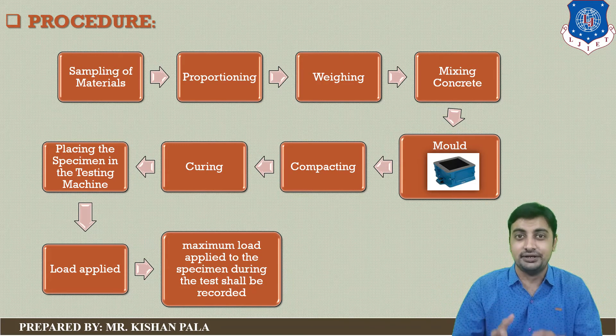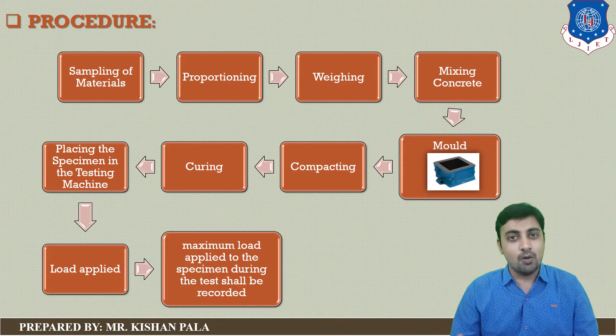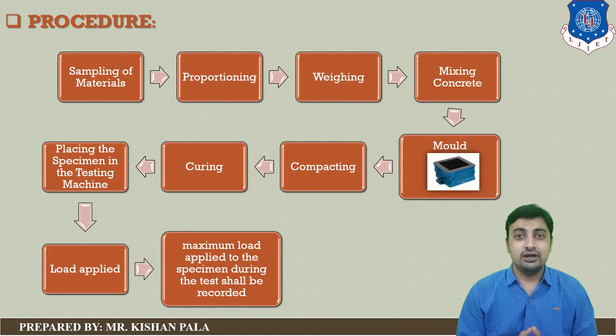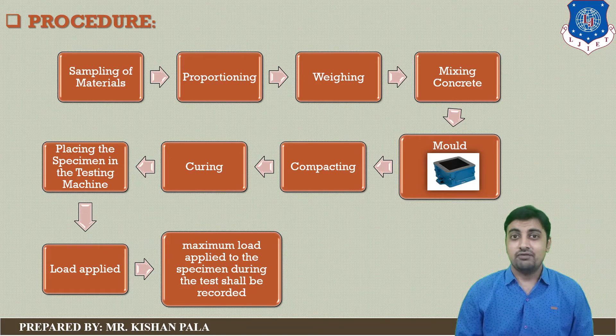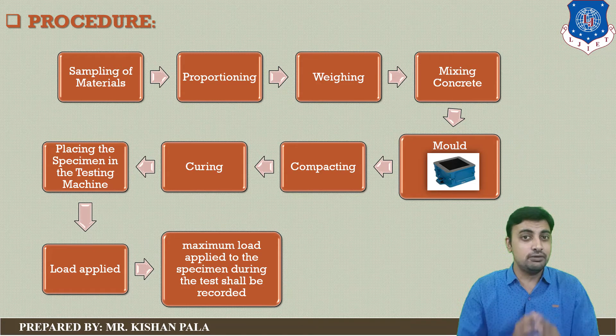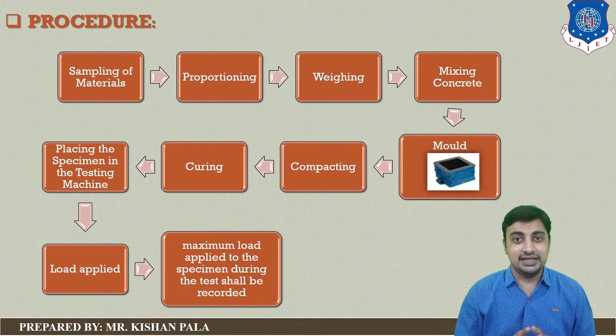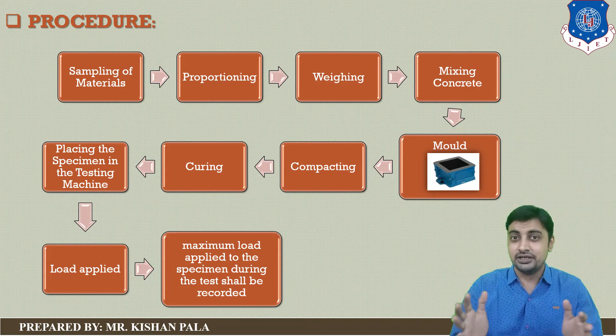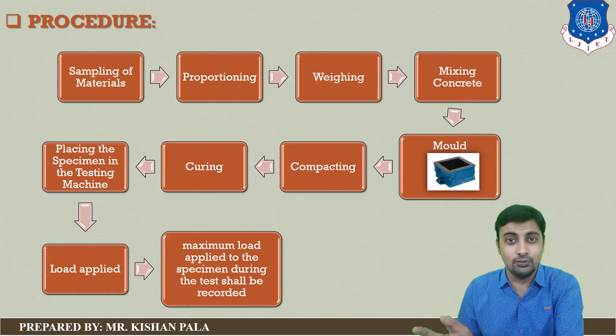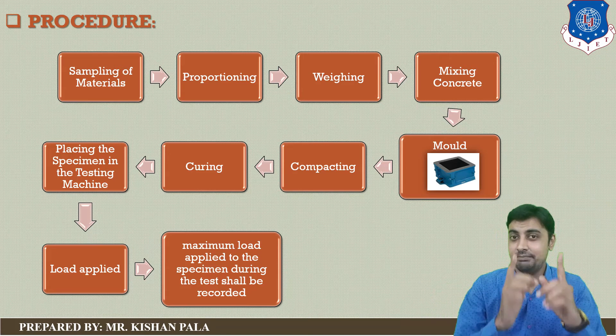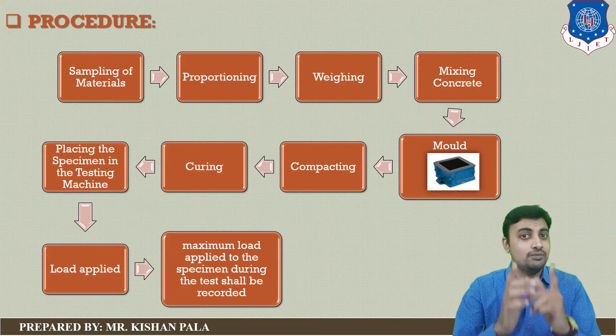After setting, you have to remove the mold from the concrete mass and place the concrete cubes in a curing tank to allow curing of the concrete mass. Generally, we find compressive strength at 7 days and 28 days, requiring 3 specimens for the 7 days and 3 specimens for the 28 days — that is, 6 cubes placed in the curing tank. Remember that the final strength is considered at the end of 28 days.